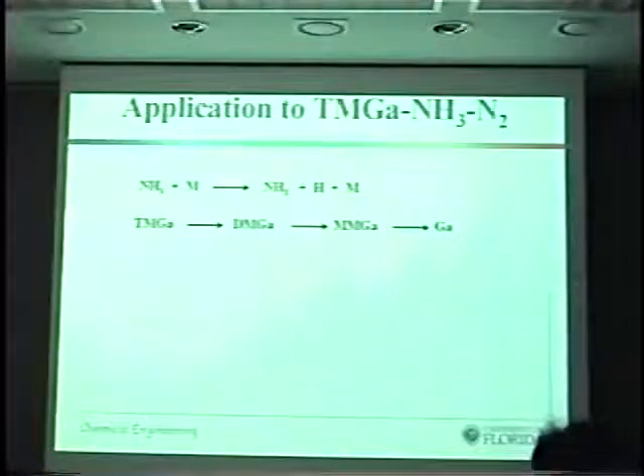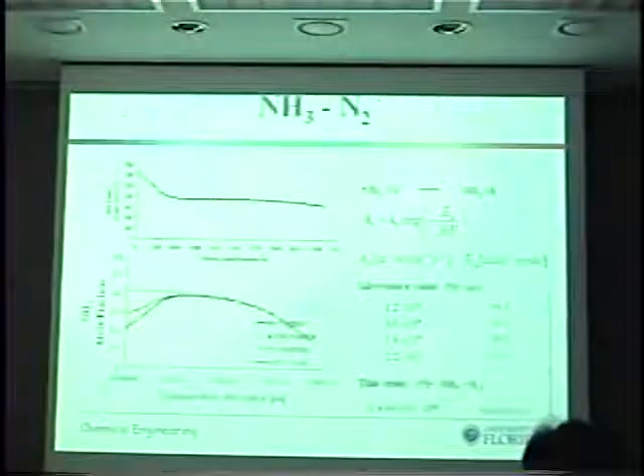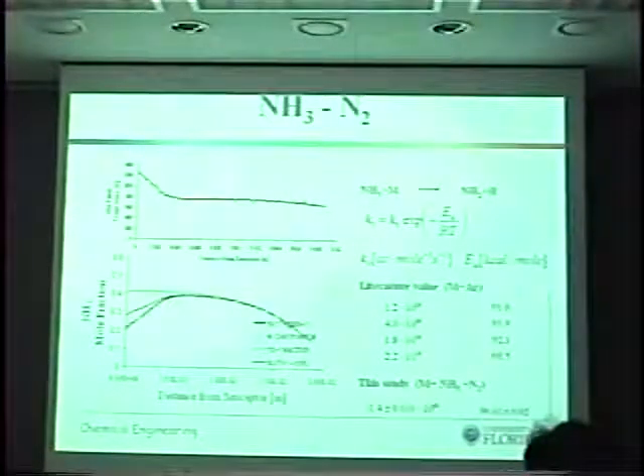Trimethyl gallium was studied in the 1970s. It was thought to undergo a sequential homolytic fission of the carbon-gallium bond, produce the dimethyl, this being a rate-limiting step, and quickly the monomethyl, which is relatively stable, and it would subsequently be converted to the element, each time giving off a methyl radical. Well, that was pretty much the state of what was known about trimethyl gallium decomposition. And so we set out to study it.